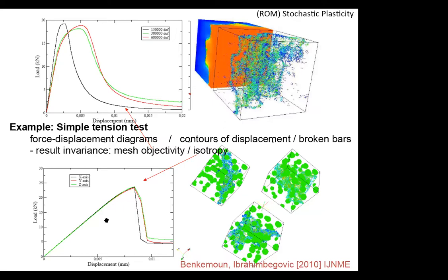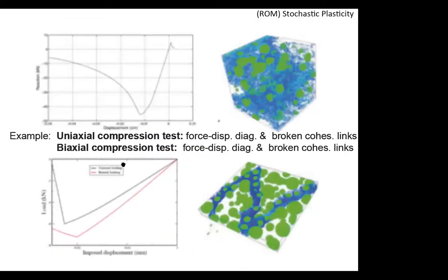And then basically the next one, if I now squish it in compression, it has many links because of the Poisson's ratio effect. Many links are being broken. And so you can see that concrete becomes 10 times more resistant in compression than in tension. It's kind of normal because you get all these links there. If I do biaxial compression, you get this typical failure pattern, okay, the links broken. And then in biaxial compression, you have it a little bit higher than uniaxial.